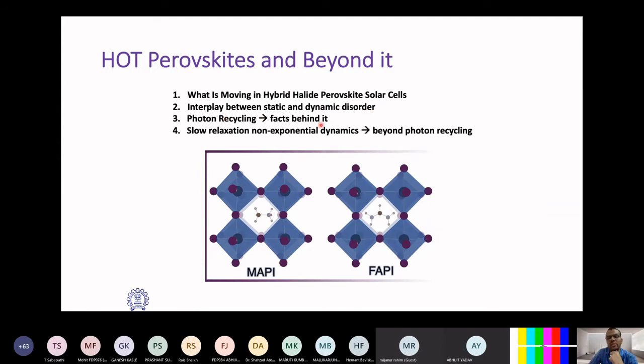Some of the papers published from various groups around the globe use lots of terminology which was already established in the gallium arsenide semiconductor. Gallium arsenide is known to give very good photon recycling. They demonstrated that some of the experimental data which they got suggest that this perovskite also has very good photon recycling. But along with us, some of the Oxford group and other groups have shown that those data were interpreted wrongly, and these semiconductors are definitely good, but not as good as gallium arsenide.